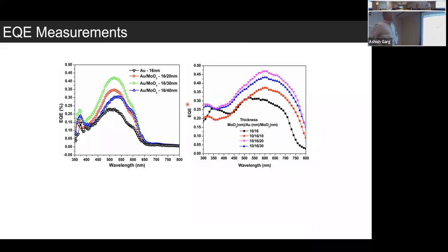And then EQE measurements show that you still have room for improvement. EQE, external quantum efficiency, is how much light is converted, and we are still close to about 50% or so. You can improve that to 70% by further using transparent electrodes. You can use transparent oxide electrodes, but the problem is you will have to deposit them by sputtering, which will destroy the solar cell. That is why we went for a metal-dielectric-metal stack, which could be made using processing that does not destroy the bottom layer.